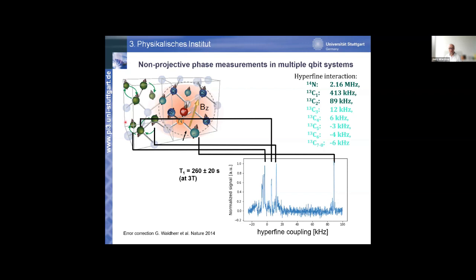The further out you go, the less strong the interaction is. And here you see a hyperfine spectrum, right? From a few kilohertz to a few 10 kilohertz. The good thing is that the relaxation time of these nuclear spins, and this is what is important here, at the magnetic field of 3 Tesla and at room temperature is on the order of 4 minutes or so. And this T1 is ultimately limiting your spectral resolution.